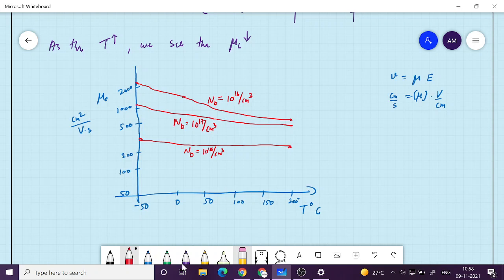So there are various mechanisms. When you measure, you can't isolate one mechanism from the other. So this mobility is not just the effect of temperature or lattice vibration, but this dependence with respect to temperature, that is entirely due to or mainly due to the lattice vibration. But the other mechanism that we talked about, which is the scattering by the impurity centers which are ionized, that is what gave rise to the lowering of this graph downward. As you increase the impurity concentration, definitely you are creating more such centers of scattering. Scattering centers become more as you increase the doping concentration. But as you decrease, the contribution from impurity scattering reduces, because the impurities are very far apart for low doping concentration, and as a result you have much lesser contribution from there.